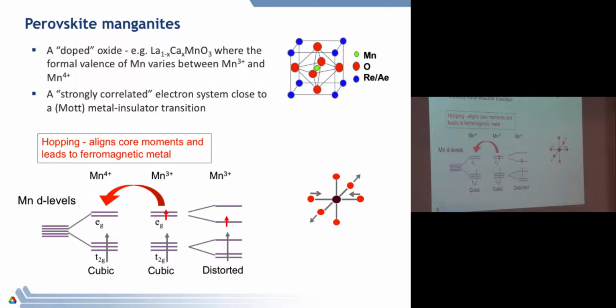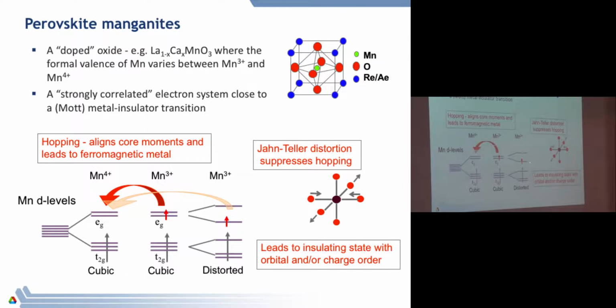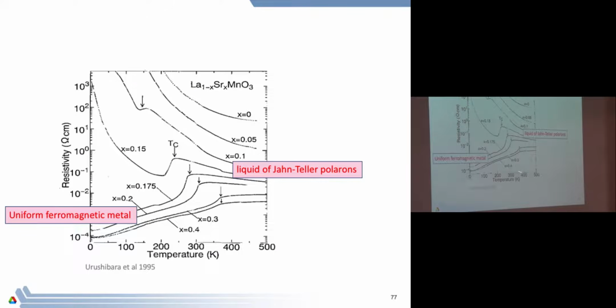But that's not the only possible ground state. The other possible state is what happens if this octahedron changes shape, because this is doubly degenerate in the octahedron state. And if this octahedron changes shape, say by 2 oxygens moving in, 2 oxygens moving out, that's called a Jahn-Teller distortion. This energy level is split, and the energy goes down. And that is clearly going to suppress the hopping, and it's going to lead to a nearly insulating state.